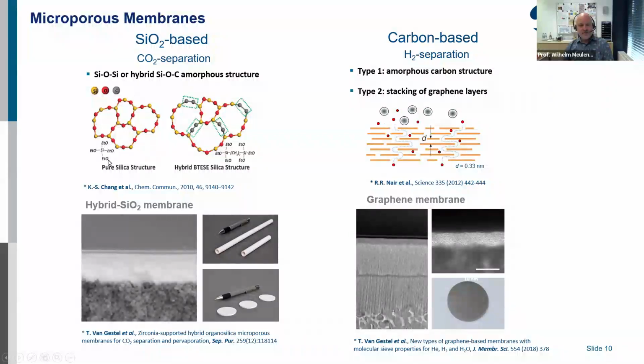But pure silica has a very quick degradation in humid conditions, which we mainly have here. And for this reason, it is stabilized by some carbon in the lattice. That means we can open the network a little bit. That means to make this open volume a little bit bigger. But in addition, it is then hydrophobic, more hydrophobic than hydrophilic. And another option of the silica membranes are carbon-based membranes for hydrogen separation. Here it is also not a pore.